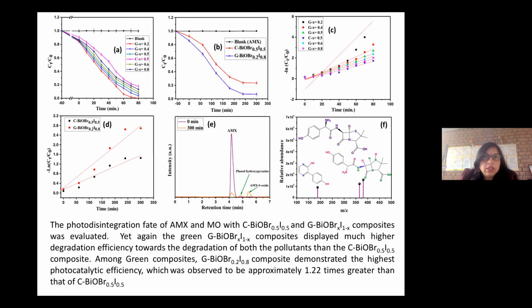For that, the degradation was shown here, and this is the blank one, no effect of anything. So it is not doing anything. Then when we check the other one, you can see the difference: when 80% I was there, it showed the maximum degradation. So this G-BiOBr0.2I0.8 showed the maximum degradation, and the kinetic study was done.